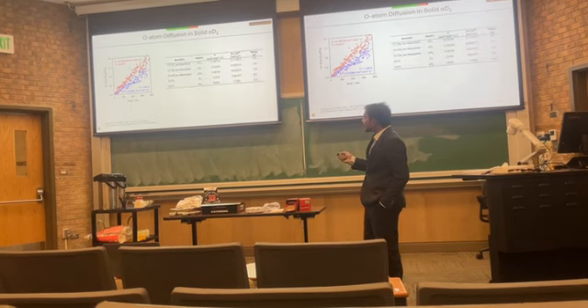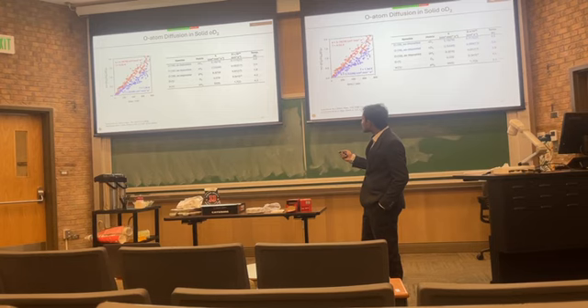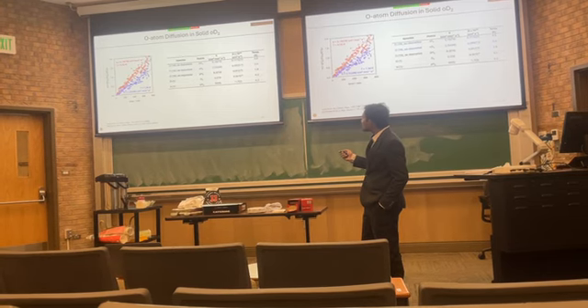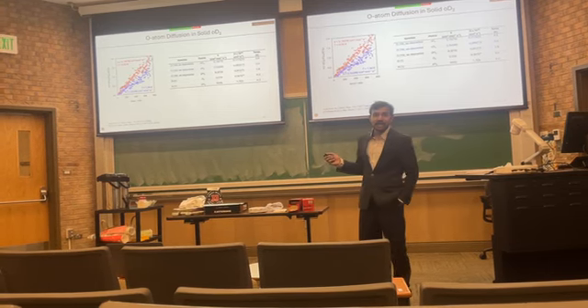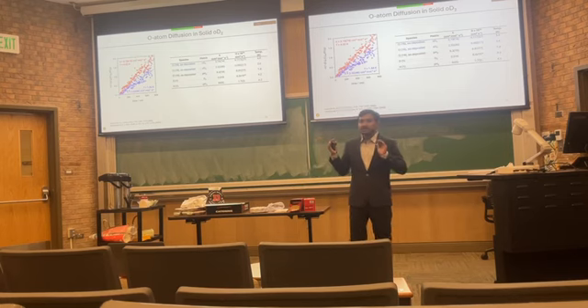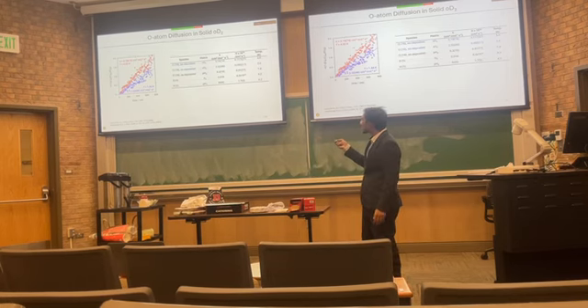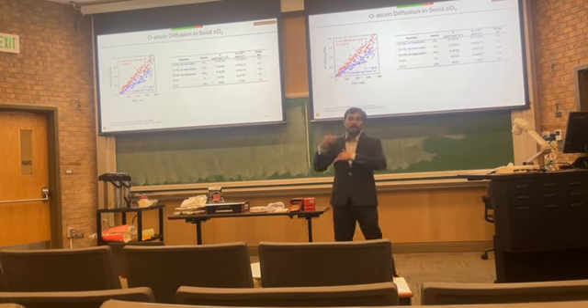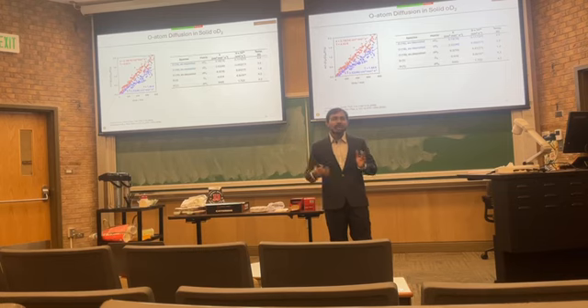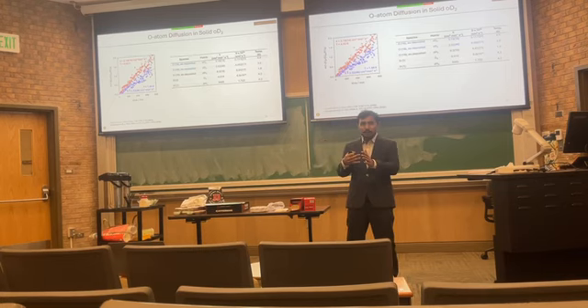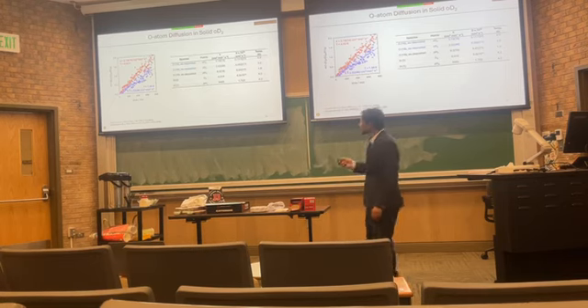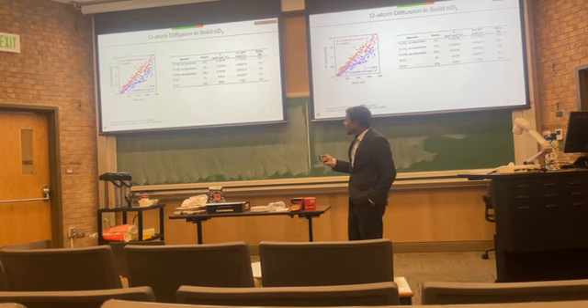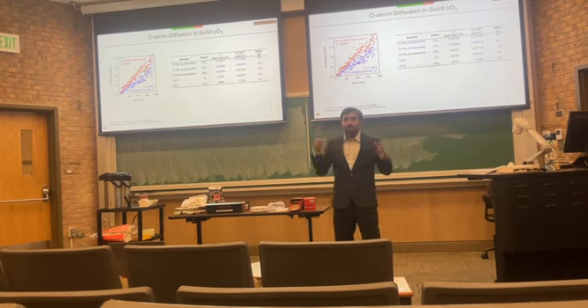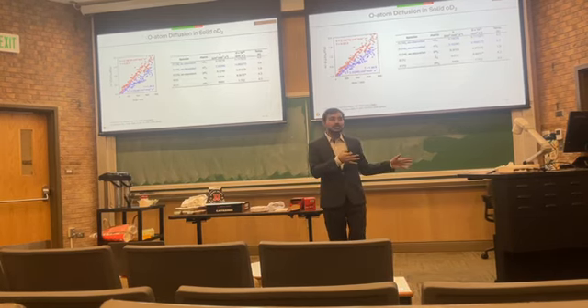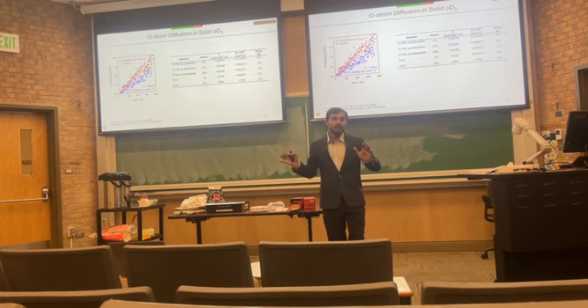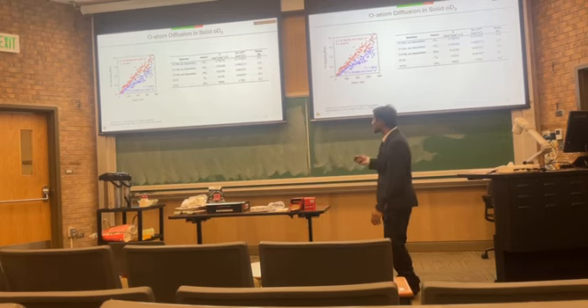Let's look at the numbers. The diffusion coefficient at 4 Kelvin and 2 Kelvin is 0.11 and 0.09. It's not too different, it's almost close, and if you put the error bars and do 10 experiments, I guess it will come closer, like it did for parahydrogen. Now, in orthodeuterium, we can only do as-deposited experiments. We cannot do annealed experiments. There are some experimental constraints.